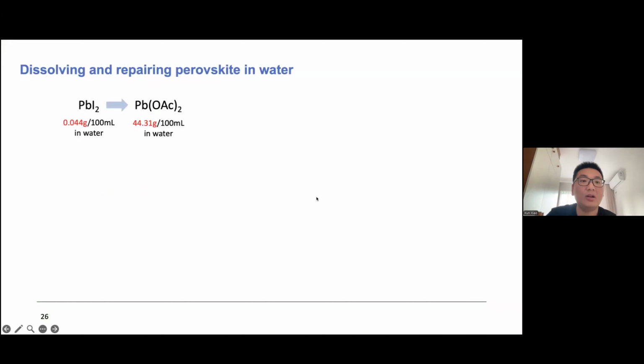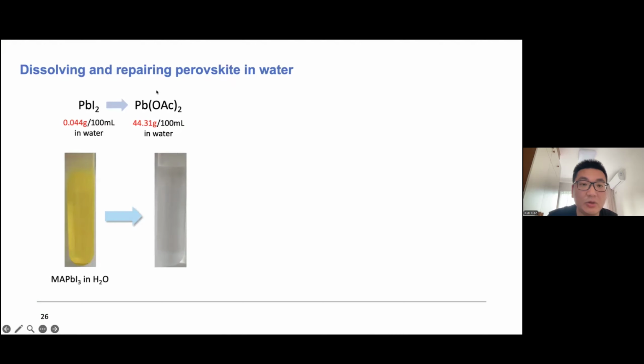So one strategy that we used in our technique is that we introduce acetate ions, using sodium acetate, to coordinate with the lead and compete with the iodide ions, because we found that lead iodide has limited solubility, but lead acetate has almost 1,000 times larger solubility in water. You can see from the picture, if we dissolve 10 gram MAPI powder in this water solution, it will have this yellow lead iodide residue. But if we add more sodium acetate into the solution, this lead iodide residue can be easily dissolved.